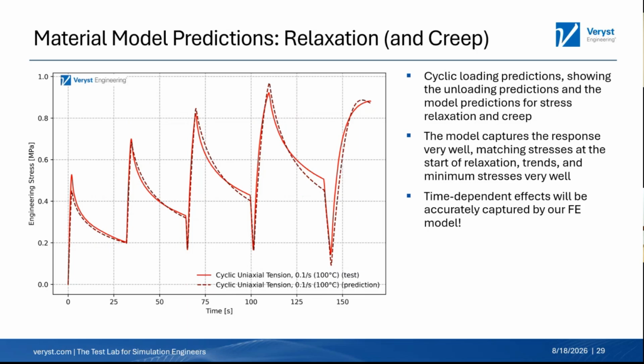But before we get into that, the other thing we want to talk about is a little bit more of that time dependence. If we look at the stress versus time for that cyclic test that we did, we can see here that we're capturing the stress relaxation very well. It's not perfect. You can see that the first two stress relaxations, up at about 0.5 and maybe 0.75 MPa, we capture very well. Getting the shape well, we're at the peak and the minimum very well. But as we go further and further up on the other two, you see the shape is a little bit different. This is just something the model isn't capturing. But overall, we're capturing that trend and that response very well.